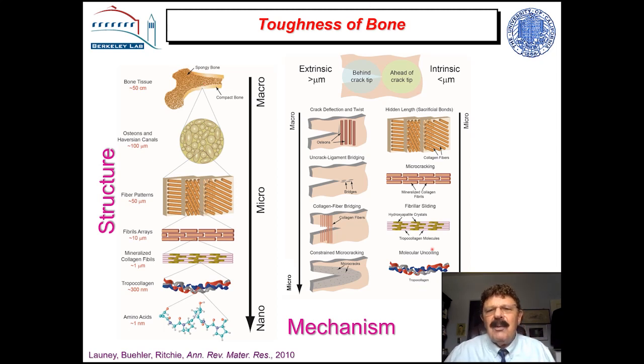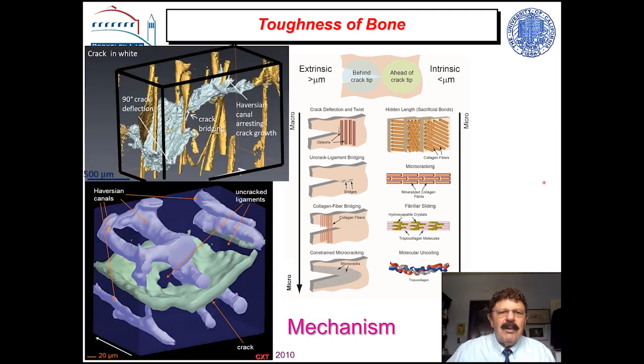At the small scales, for example, below a micron, ahead of the crack tip, you see intrinsic toughening from plasticity. Plasticity in bone is generally many mechanisms, but generally it's the stretching of the collagen fibrils and then them sliding apart. That's fibrillar sliding. Anything that inhibits that will tend to inhibit plasticity. If you look above a micron behind the crack tip, you see all the extrinsic mechanisms that you might see in a ceramic: microcracking, bridging by collagen fibrils, little regions between the microcracks that act as bridges, and deflection at the collagen fibrils. I have a few images of this from tomography.